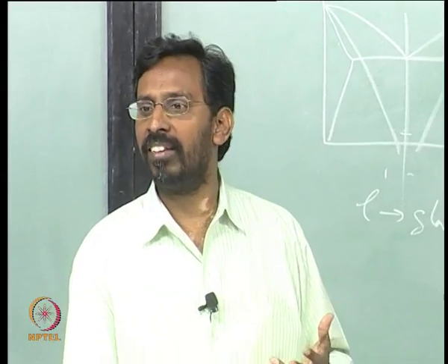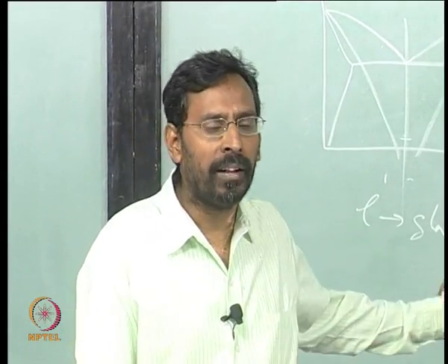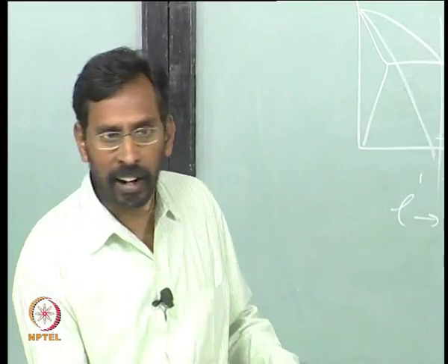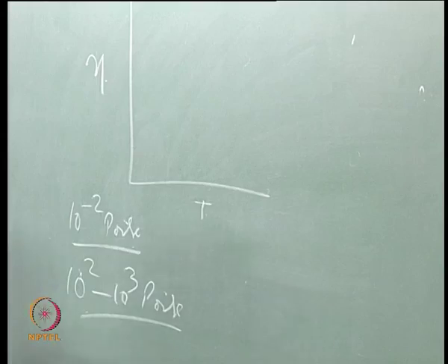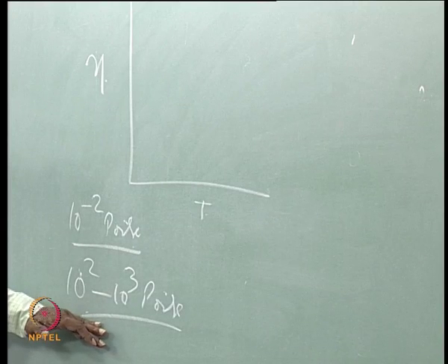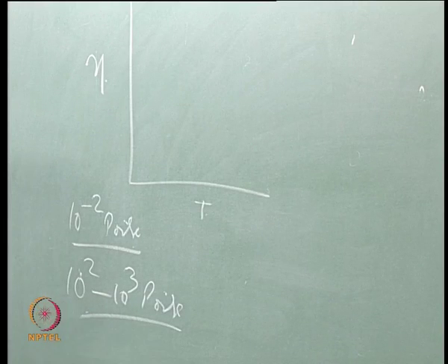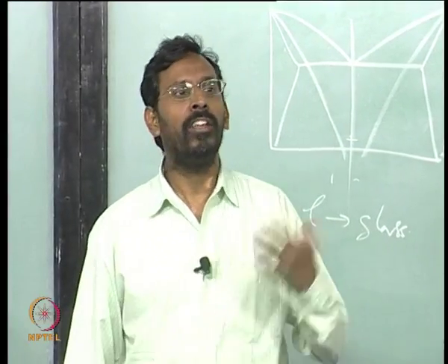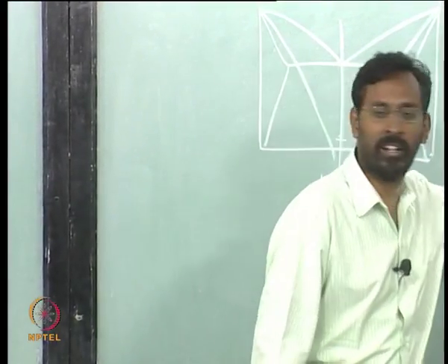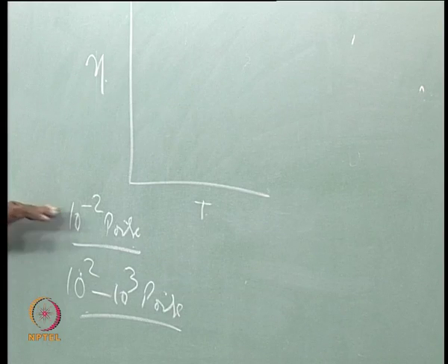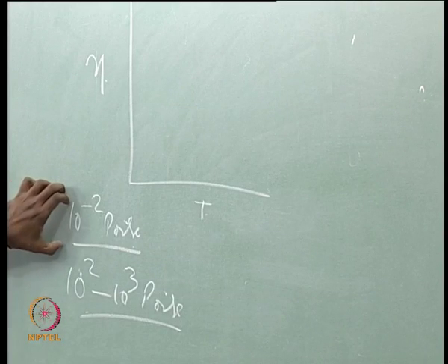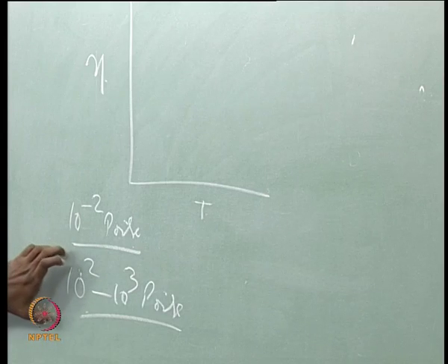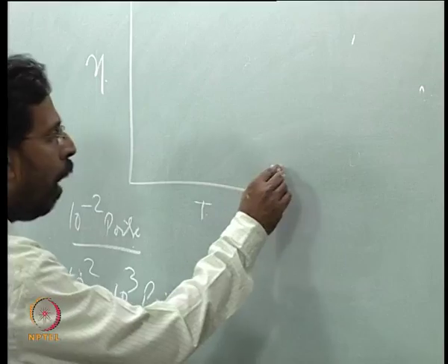The silicate clusters that are there in the liquid will make this liquid very viscous, and that is the reason why we always say glass formation in these liquids is easier, because for them to nucleate a silicate crystalline solid is more difficult when compared to metals. Atoms can easily move when they are less viscous; when it is more viscous, atoms are not able to move. And now if I plot how this